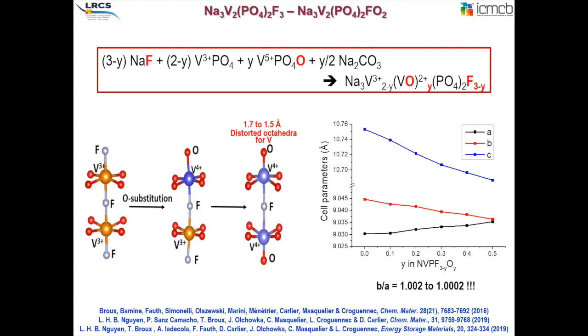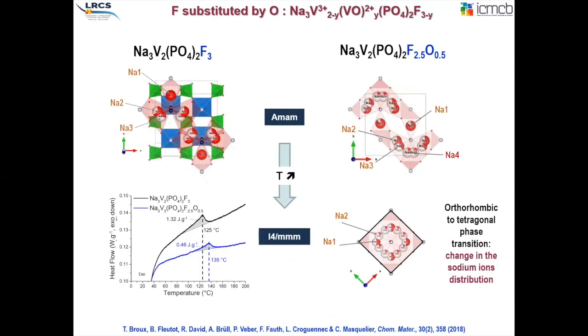We made very clear tables of the evolution of the lattice parameters as a function of Y in the fluorinated oxygen-substituted samples. And you can see that as soon as we reach 0.5 oxygen, basically the structure is not orthorhombic anymore and transforms to a tetragonal unit cell. Depending on the amount of fluorine versus oxygen, the compounds also show different thermal behaviors.